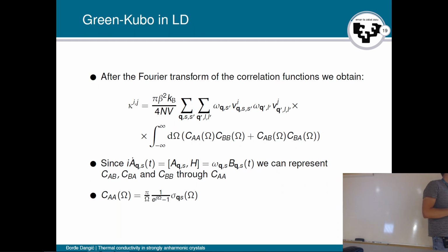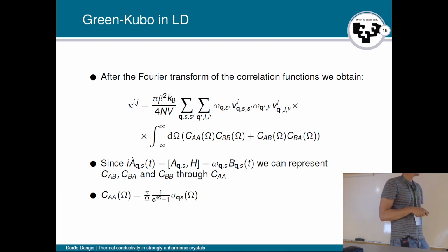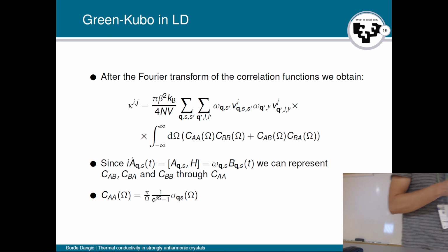Okay, so here, as you can see, we will have to calculate 4 different correlation functions, right? CAA, CBB, CAB, and CBA. And in the previous talks, we only got the CAA. But since the time evolution of this operator is governed by the Heisenberg equation, and the position operator commutes with the higher anharmonic terms, we are left with a very simple connection between the time derivative of the position operator and the momentum operator. And of course, if we take the Fourier transform of this, we then get a linear combination between A and B, which allows us to express CAB, CBA, and CBB through the correlation function CAA. So we only need CAA.